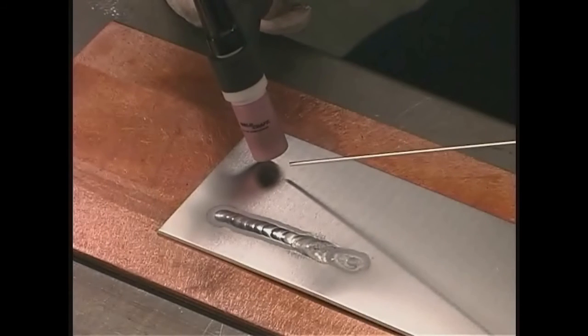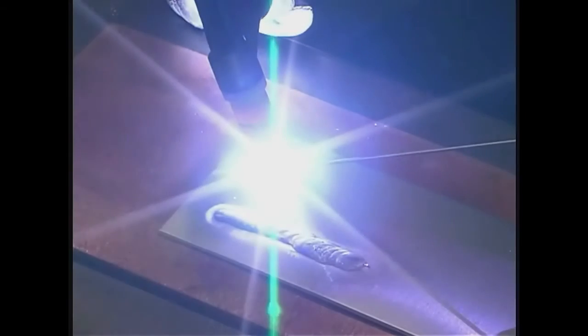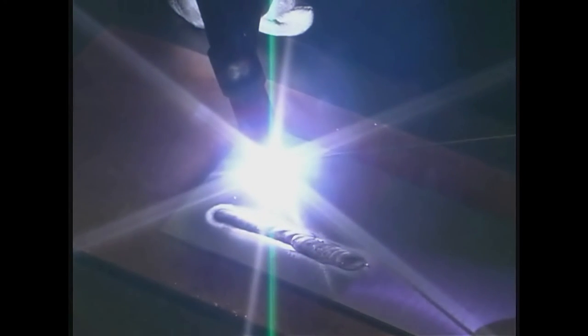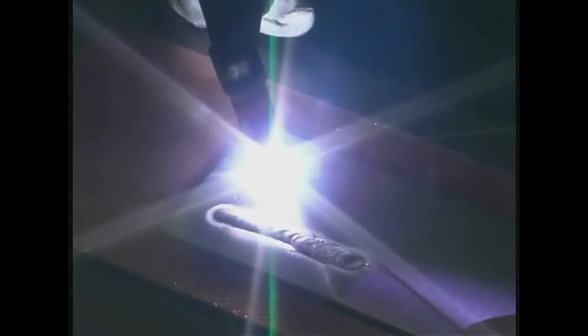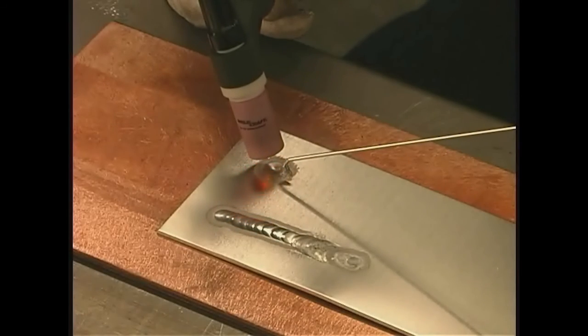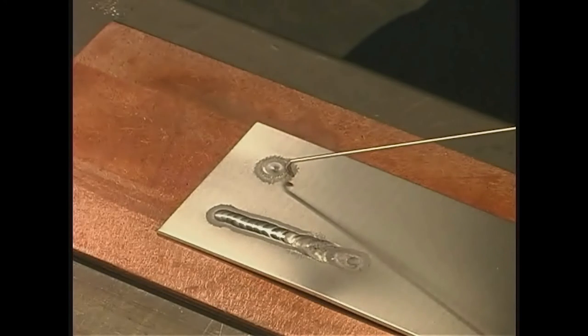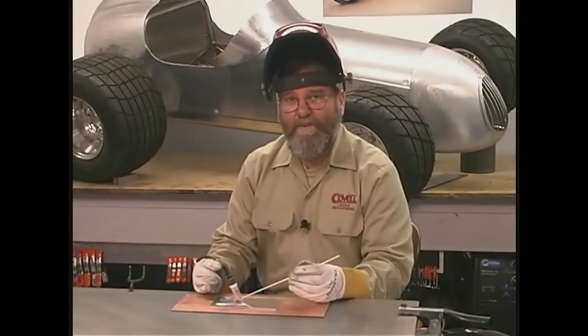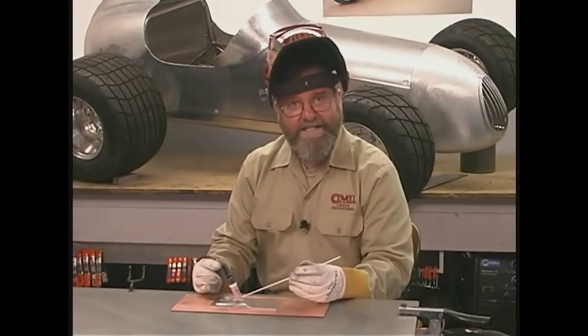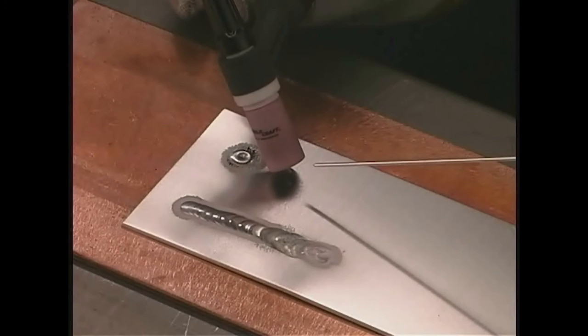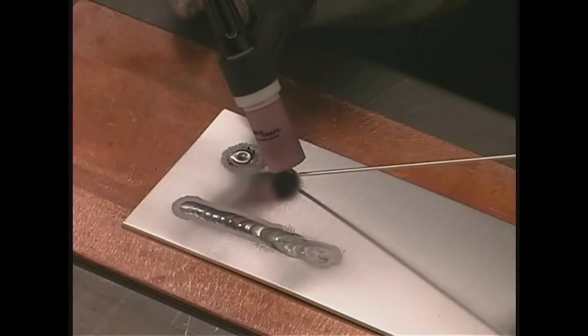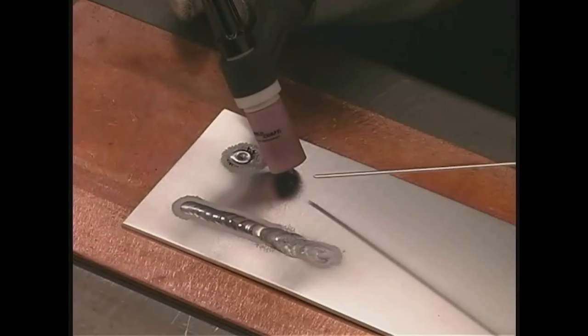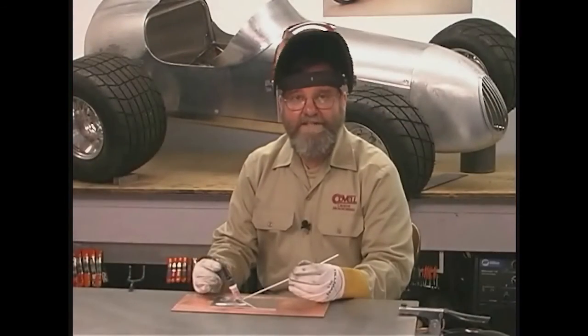There's a problem with holding the filler rod too close to the electrode. If the welding rod is not withdrawn sufficiently, a big blob will form on the end of the rod. So you need to withdraw it enough that this doesn't happen. But it's also important that you not withdraw the welding rod too far. The end of the rod needs to remain within the argon gas shield. If you pull it outside of that shielded area, the hot end of the welding rod will oxidize. And then when you dip that oxidized rod into the puddle, you're bringing contamination into the weld.